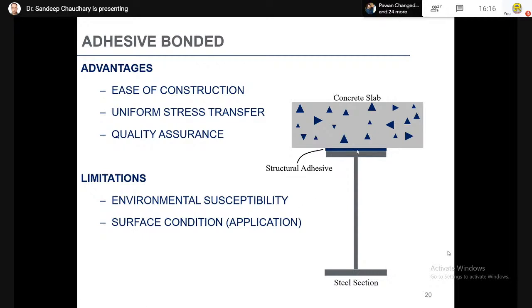And you also have to ensure the surface condition is very good. The reason is that when you use these epoxy adhesives, the thickness will be hardly 5 mm or 10 mm, not even more than 5 mm. And if there are undulations in your surfaces in the range of 3 to 4 mm or 5 mm, then there is no purpose in using these adhesives, because there will not be a proper bond. So that has to be ensured.